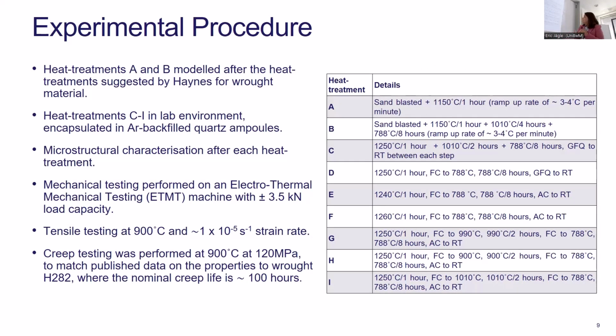So the first couple of heat treatments were what we call the industrial ones. So we sandblasted the samples. This seems to be a standard thing for the surface finish for this particular application. And then we had the 1150 degrees Celsius for 1 hour solution heat treatment or homogenization heat treatment, followed, so the first heat treatment is just that, just the solution, and then we have the two-step aging attached to that for the second one.